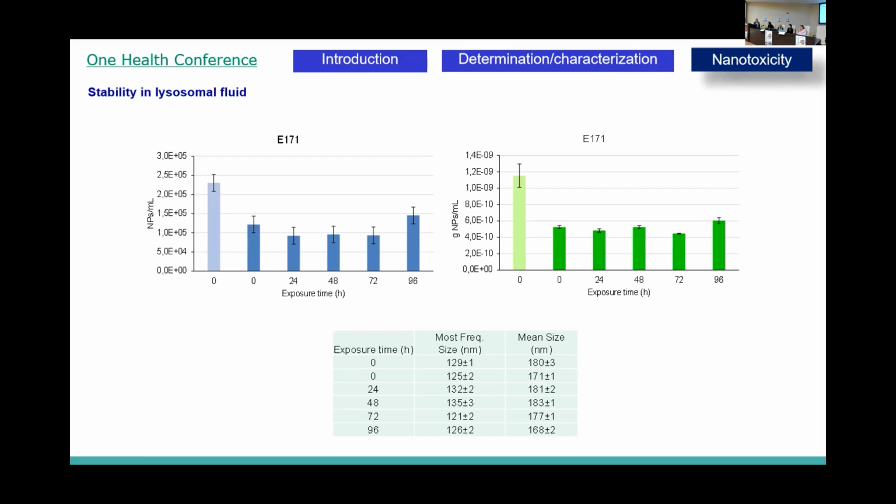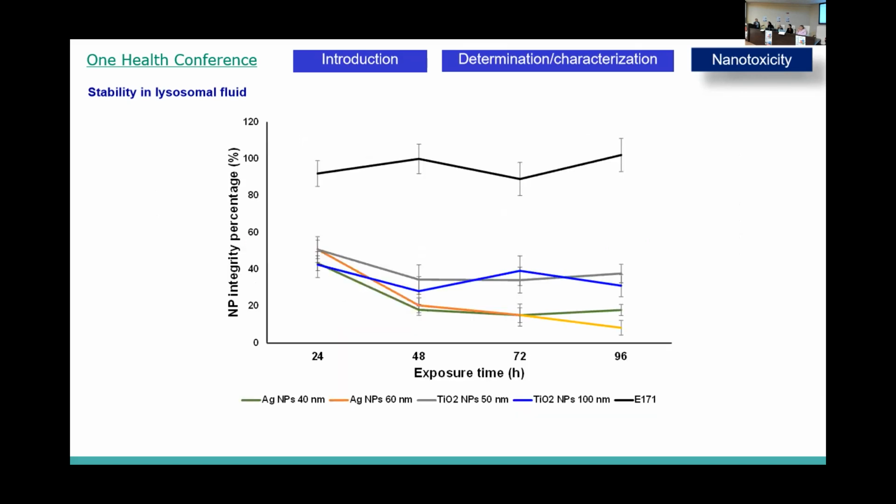So this implies that this food additive is not degradable under lysosomal conditions, and that we can find the nanoparticles after a very long time inside the cells as nanoparticles or as microparticles, because this food grade additive contains both types.